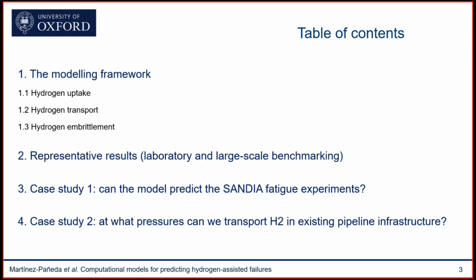And again, this is another area where models are critical, because we know that the conditions relevant to welds are very difficult to replicate in laboratory experiments. And it's also very difficult to run experiments on real large-scale pipes, because we know that there's an oxide layer that takes significant time or significant action to be disrupted, and that oxide layer prevents hydrogen uptake. So you may be running these very expensive large-scale trials and getting nothing out of them, basically. So models, again, can make a difference.